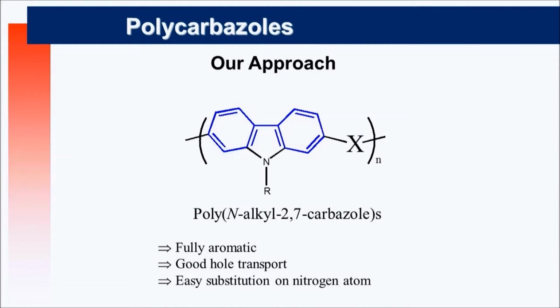So it started with a graduate student. He's now Professor Jean-François Morin. He wanted to make an original contribution to the field. And he came to me, he said, I would like to work on polycarbazoles, in the 2000s roughly. And if you want to make it conjugated, you have to link the carbazole units at the 2,7 positions. If you start with carbazole itself and you want to activate the 2,7 positions to make a polymerization reaction, it's almost impossible, because the most reactive positions are the 3,6 positions, in the para position of the nitrogen atom here. So I told him it's a good idea, but it's not possible. Nobody has done that. It's a dream, but we don't know how to make it.